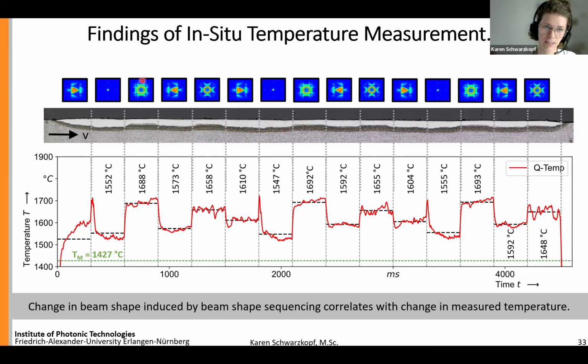And what is now interesting to see is that those beam shapes, basically the ring and the square, that exhibit the least penetration depth exhibit the highest measured temperature. And what is again interesting to see is that we can really get a change in our temperature measured, depending on our beam shapes.